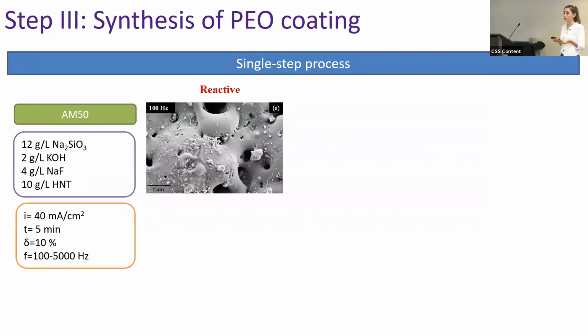So we've tried both approaches, and in the single-step process, we studied a commercial magnesium alloy, an AM50 alloy, using a standard electrolyte, a silicate-based electrolyte, and we incorporated some nanocontainers. And we observed, as we feared, that all of the nanocontainers were completely destroyed during the process. So this agglomeration here are melted nanotubes. This means that the temperature within the plasma microdischarges was too high, and it led to the thermal decomposition of my nanotubes.